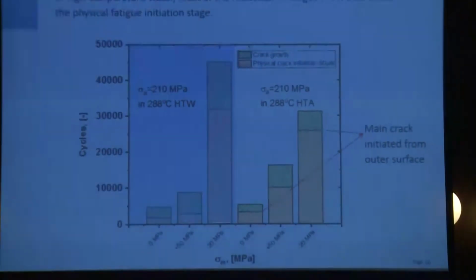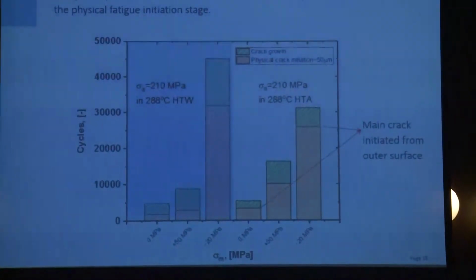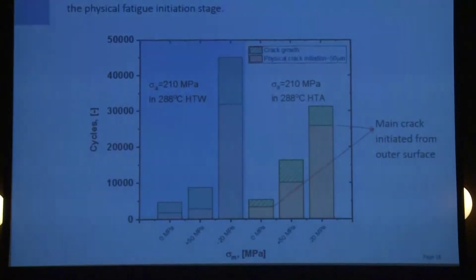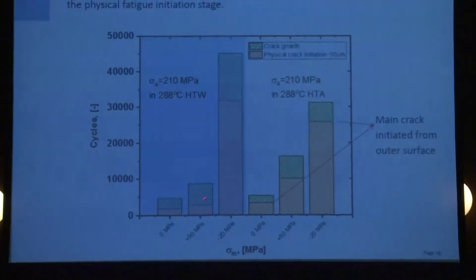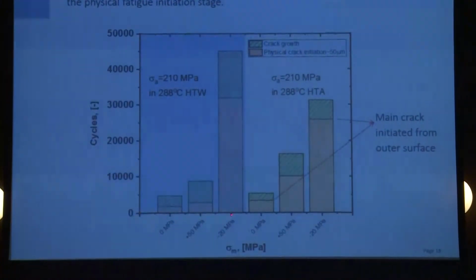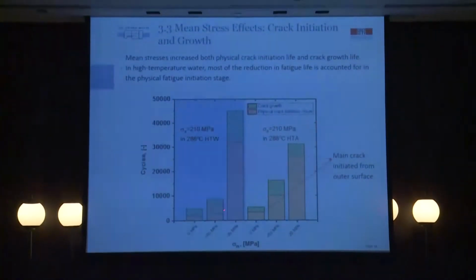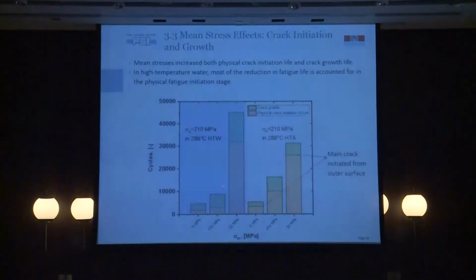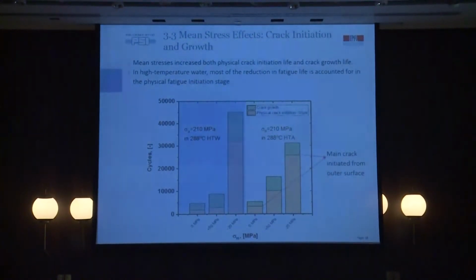And with the measured crack growth cycles, we can calculate the physical crack initiation cycle. This is the crack growth cycle. This brown is the crack initiation cycle. We compare the cycles of the two different stages with different mean stress. We found that the mean stress, both positive and negative mean stress, has increased the fatigue life cycle in both stages. And a similar phenomenon was also found in the high temperature air condition.